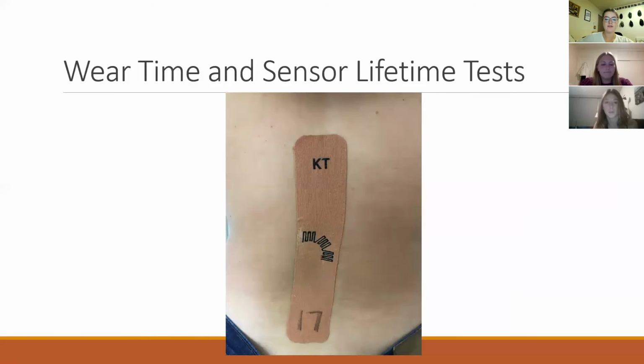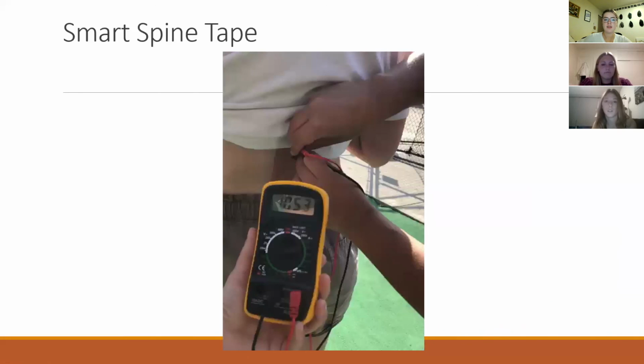The longevity of the device was measured through a 24-hour wear time test, ensuring that the tape remained secure. The sensors on the tape were analyzed to see if there was any change in resistance over the time period. The sensors were less reliable after the 24 hours and not able to get a consistent reading, but there was still some ability to measure changes in resistance. Additional tests were performed to measure the size of the tape and the time it takes for application to ensure ease of use for the users.